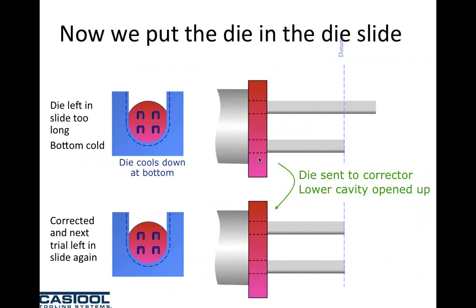Say we left the die in for 5 minutes, and we reduced the temperature of the die at the bottom by 100 degrees. Back to my rule of thumb, we would expect about 10% more flow through the top of the die than the bottom. The die corrector would choke the top bearings, and the next time the die goes to the press, if you left it in the die slide for 5 minutes again, it would be fine. But if you don't get the butt stuck on the butt knocker this time, and you actually extrude quickly, the back holes now will hold back, and the bottom holes will go through. And your die corrector will be chasing this.